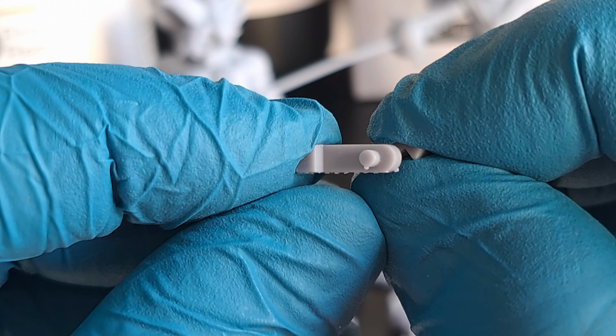With a tensile strength around 36 and flexural strength around 56, this resin can handle pulling, twisting, and bending forces, and that's exactly what parts like gears and couplers go through during normal use. The viscosity is around 450 CPS, which means it flows well and prints consistently. Linear shrinkage is listed at under 2%, and that shows in real use. Press fit parts like gears and couplers fit the way they're supposed to without guesswork.